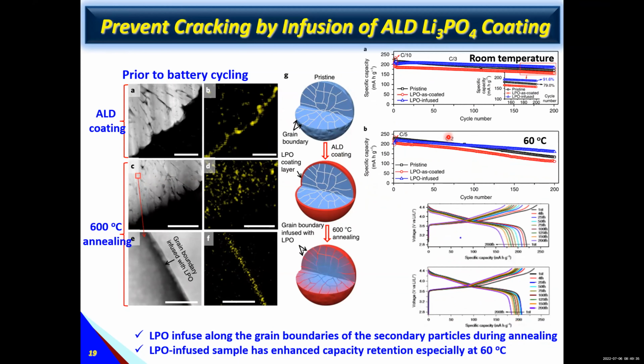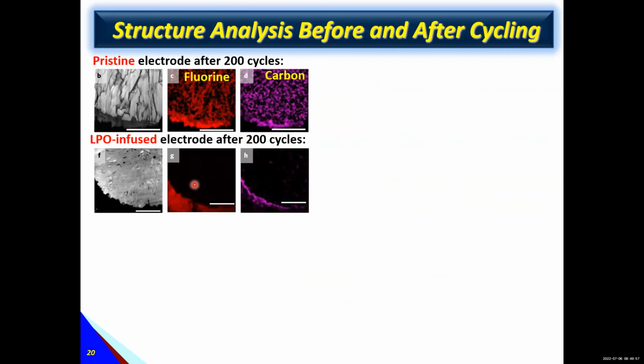So we tested the performance, and we found, yes, with the coating and annealing, the cycling retention is much better, from almost 79% increased to 91% after 200 cycles. At higher temperature there is a bigger difference. We also try to understand what happened. Actually, without coating and annealing, we see there's liquid-based electrolyte penetrating inside. We have a fluorine signal, carbon signal from liquid electrolyte. But with coating and annealing, you cannot find that fluorine and carbon signal inside.